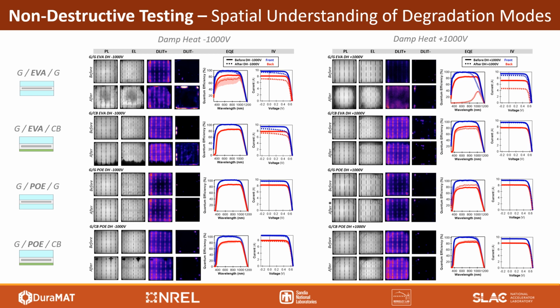Now we can get even more insight into the changes in IV metrics using non-destructive spatially resolved analyses. Here I'm showing just the negative bias and positive bias damp heat, since those are the conditions where we saw the most degradation. For each module, we recorded images of photoluminescence and electroluminescence, labeled here as PL and EL, as well as the dark lock-in thermography under forward and reverse bias conditions, labeled as DLIT plus and DLIT minus.